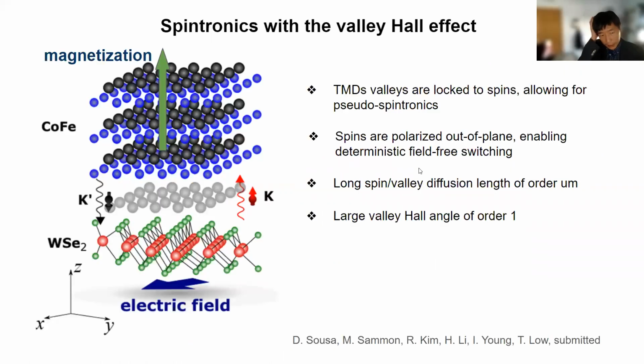So let's look at the first proposal that we have to try to overcome the limitation of trying to acquire Z polarization so that we can switch perpendicular magnetization. One of the first ideas that we look at is using transition metal dichalcogenides. These are 2D semiconductors which have a rather large spin-orbit coupling. They have a Brillouin zone that is very analogous to graphene, which has this hexagonal Brillouin zone, and for the monolayer case, the conduction and the valence band are direct band gap, and they reside at the K and the K prime points.